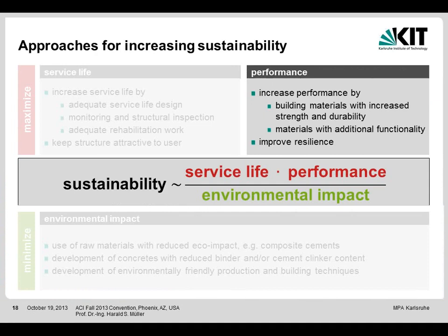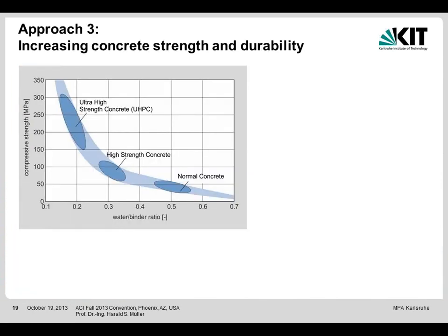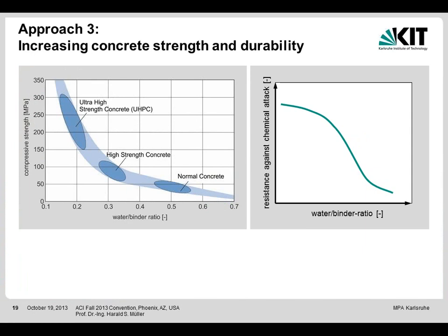The performance may be increased by increased strength and durability, by materials to be applied with additional functionality, and by an increase of the resilience. Everybody knows if you reduce the water binder ratio, we arrive at high strength concrete, and for very low water binder ratios, we arrive at ultra high strength concrete, which can have a very, very high strength.